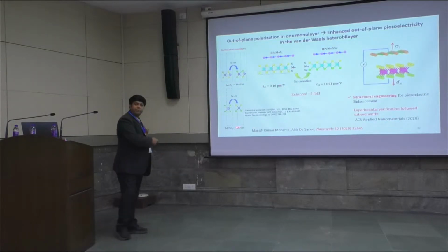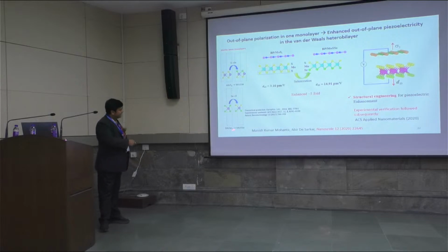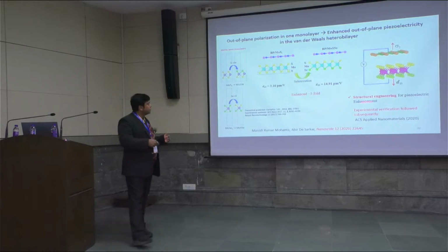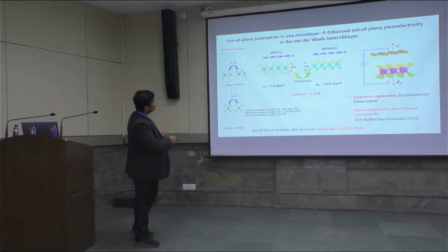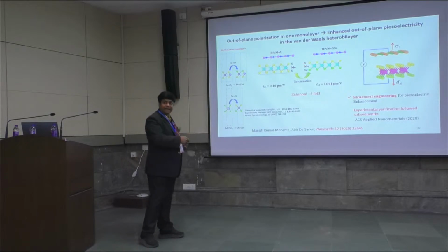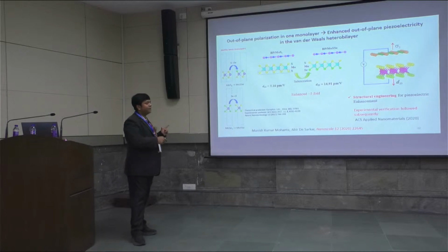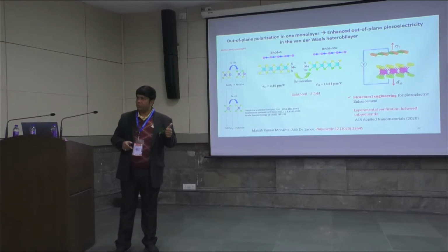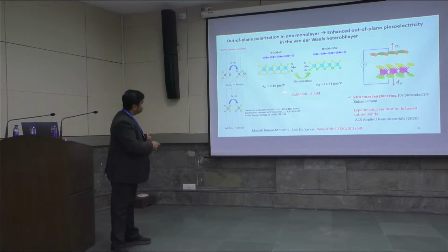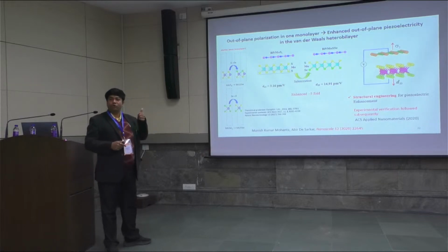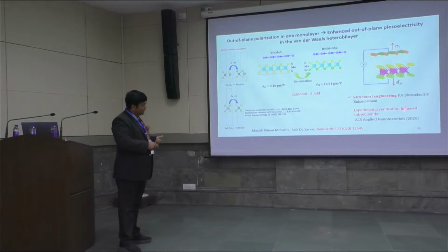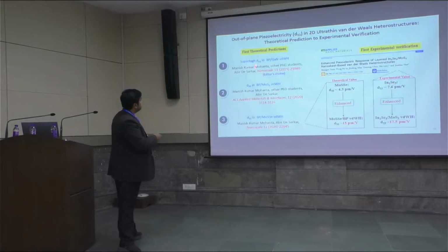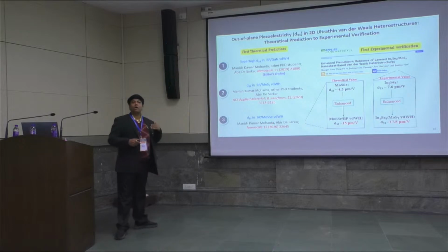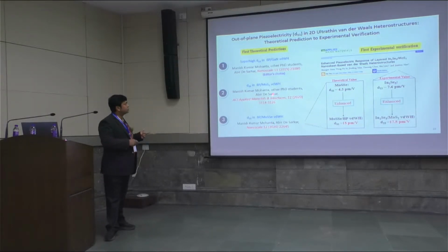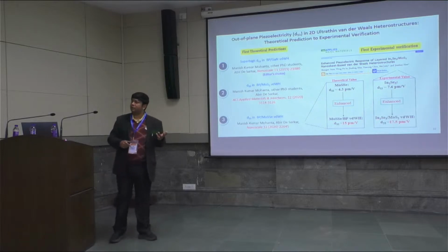Now, moving on. Janus structures have been experimentally synthesized. MoSSe has been experimentally grown. So what if we replace MoS2 by MoSSe? If we introduce a mild out-of-plane polarization in one of the individual monolayers, we find a five-fold enhancement in the out-of-plane piezoelectric coefficient, which has been confirmed experimentally on a similar system. So in summary, these are the first theoretical predictions of the occurrence of out-of-plane piezoelectricity in van der Waals heterobilayers, which has been confirmed on a similar system, and they have cited our papers, and that's how we came to know.